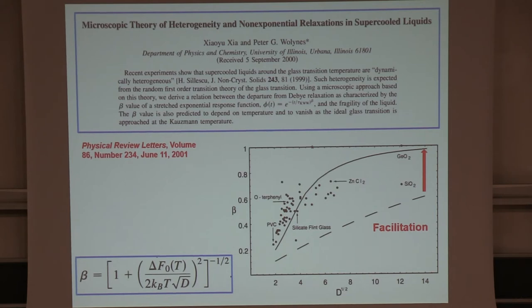What's the origin of this? The origin of this is that the distribution of deep traps is too broad. It's too broad because if all of the regions around you have reconfigured, you have no way of knowing you're supposed to be pinned where you were before. Your surface energy has gone down. And so this is actually a facilitation effect, which, if you take that into account, gives you this curve, which you can see goes through the data quite well.